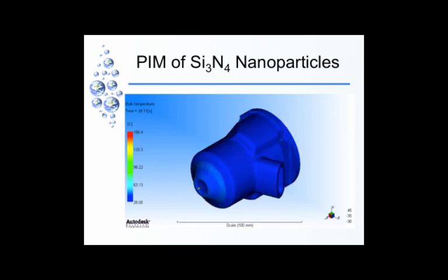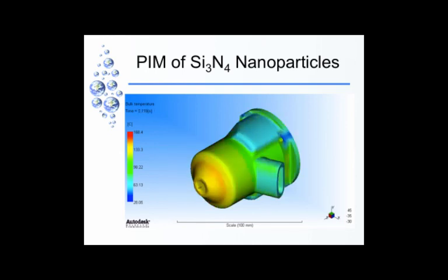But now you're beginning to understand that you find out how much powder you can fit into a polymer. Then you look for all the properties that you can measure. You put that into a simulation platform. You see if you can make the part or not. Then you make some test parts and you sinter them and see if you can make it correctly, what the properties are. And then you scale up with a mold, things like that.